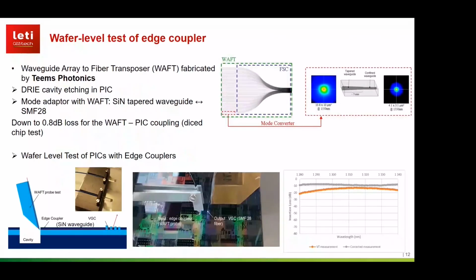Okay, so we had some preliminary tests. If we couple a WAFT and a chip, not this scheme, but a diced chip of silicon nitride taper and a WAFT, the smallest loss we saw was 0.8 dB. And in this case, the alignment was not so easy, and so you have on the right the losses as a function of the wavelengths, and it's around minus 10 dB. So it's a high loss, but the point of this scheme is to test circuits with edge coupling. So we don't mind if there is 10 dB at the input. It's just to test that the circuit is working. So it's not a problem for us.